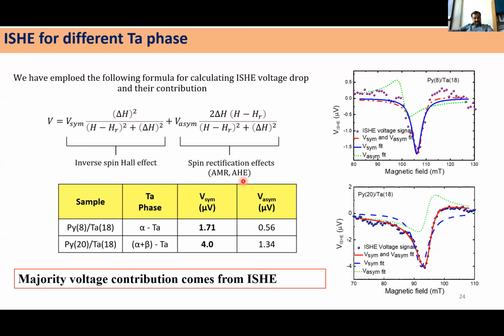And as the previous talk mentioned, it cannot be truly attributed to the inverse spin Hall effect alone. It could be because of spin rectification effects also. So to decouple, we have fitted this data with a symmetric component and an asymmetric component, and we found that the majority of the signal is coming from the symmetric component. That tells that the inverse spin Hall effect is there in our samples.